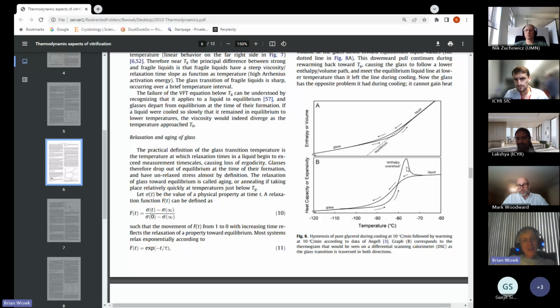So if you're relatively close, and by relatively close, I mean 10, 20 degrees of the glass transition, the glass will relax over years and centuries, but I can't think of any cryobiological significance to that other than the benefit of having less thermomechanical stress.